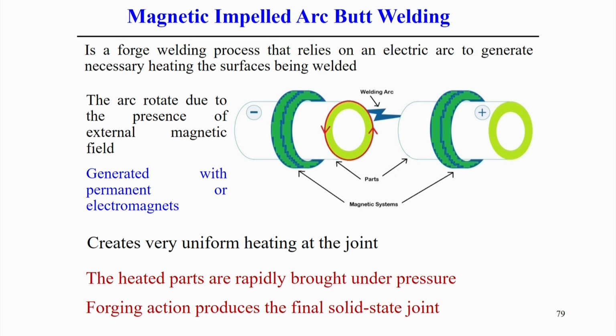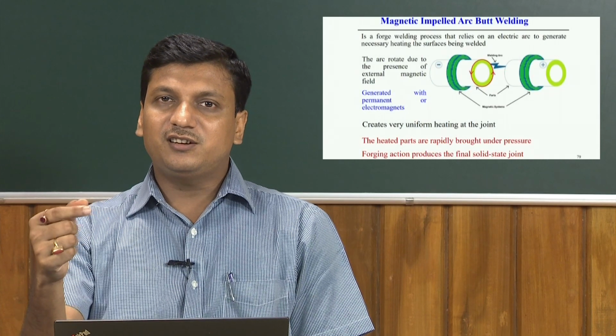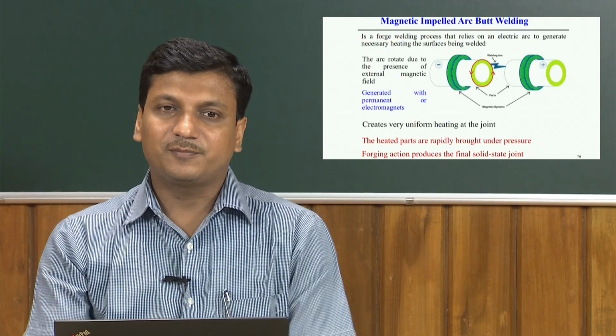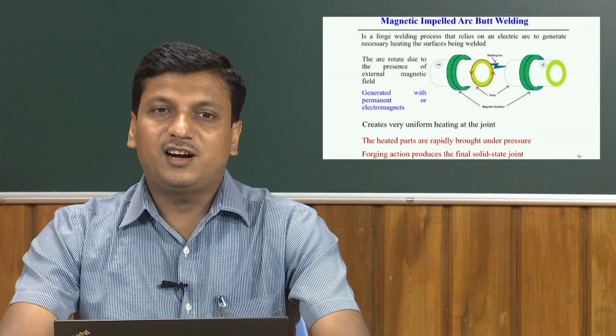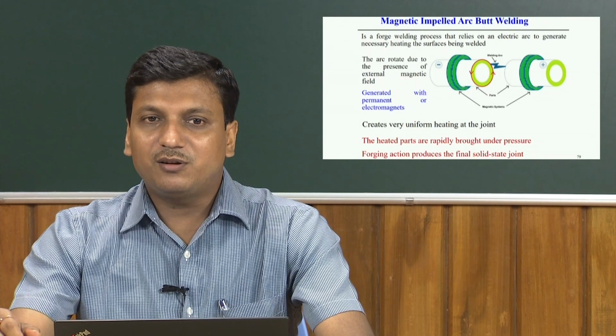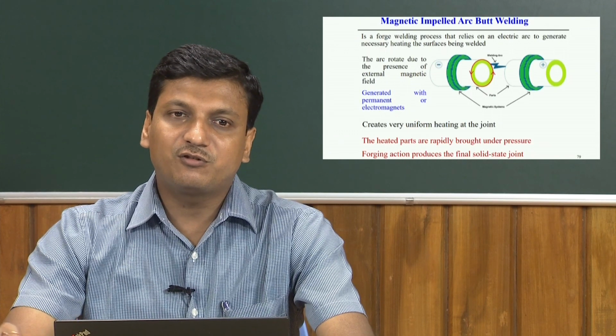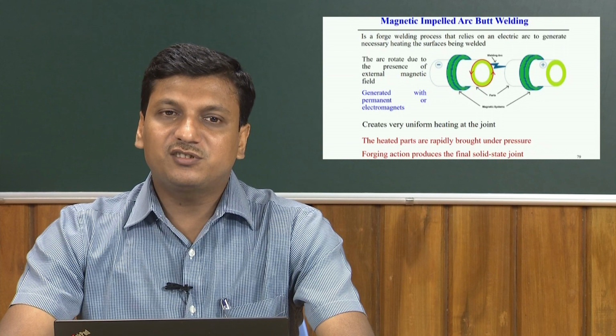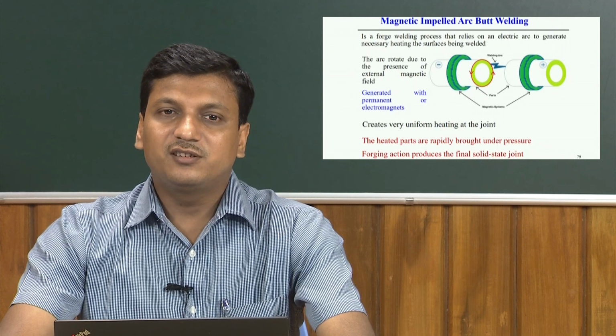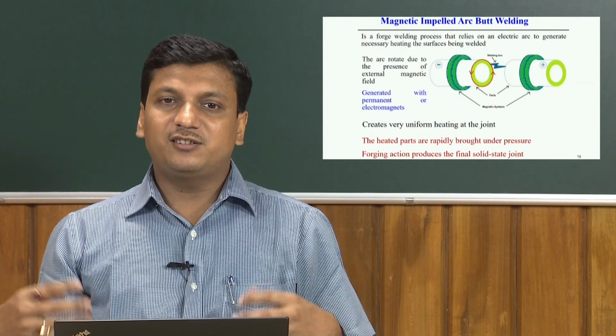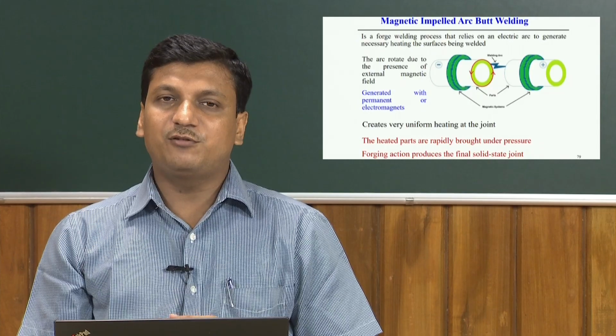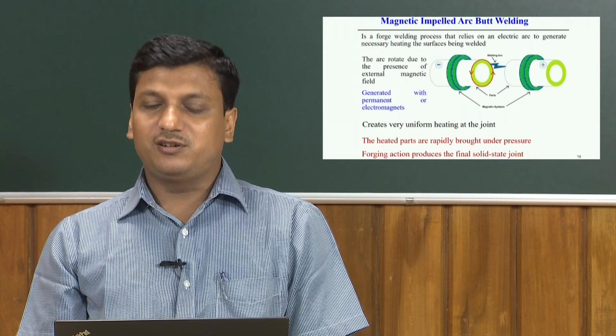But what is the role of the magnetic field here? The magnetic field is created to rotate the arc. After the arc starts, the magnetic field is controlled in such a way that it rotates the arc, so that it can create the arc between these two components throughout the whole circular section. This magnetic field is generated with a permanent magnet or from electromagnets. The advantage of this process is that it creates very uniform heating at the joint. The heated parts are quickly brought under pressure, and the forging action produces the final weld joint.